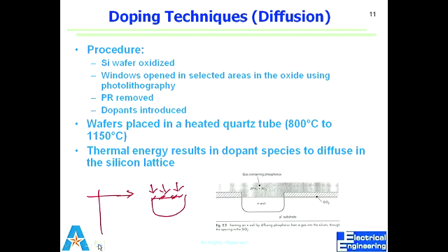Will I have my N-type well left there? Will I have my source region? Does it make sense what I'm saying? So we do doping, and we know, okay, this is the region where I have X number. So 10 raised to 10 was the background concentration. So I doped it to 10 raised to 18. But now I did another thermal process. I might have come back to maybe 10 raised to 10. The electrical properties of that area would be completely changed. So that is what is called back end of line process and front end of line process.